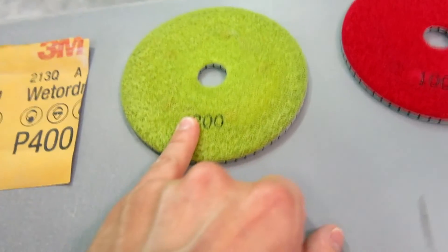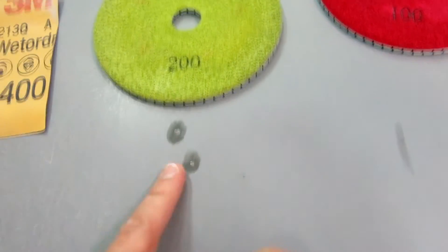Now this is very hard concrete. If your concrete's really young, you may want to stick to the 200 and not be so aggressive to expose sand grains and take away your cream.